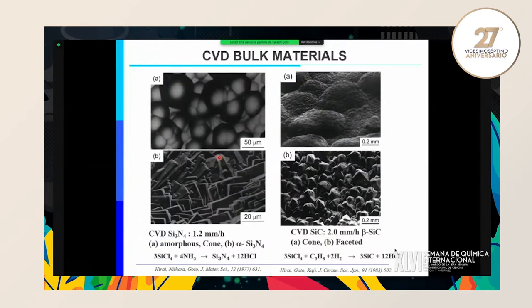And by using cold wall CVD and by using a not so reactive precursor like silicon chloride, we can make silicon nitride or silicon carbide bulky material at high deposition rate, 1.2 millimeters per hour or 2 millimeters per hour. Some company people came to my lab, studied CVD, and commercialized bulk CVD material.